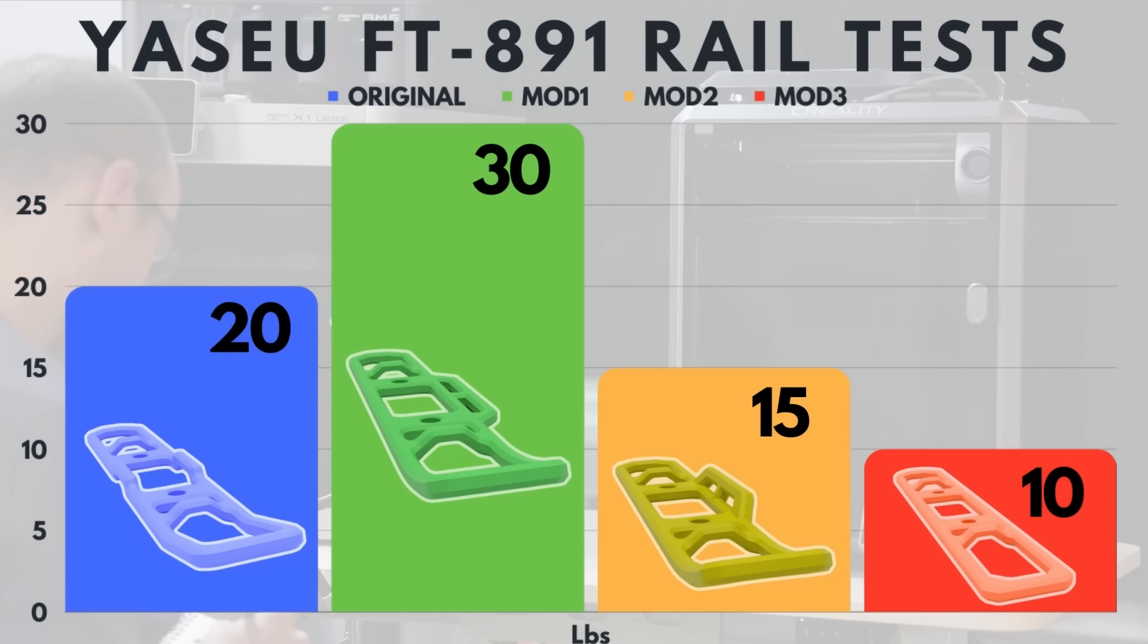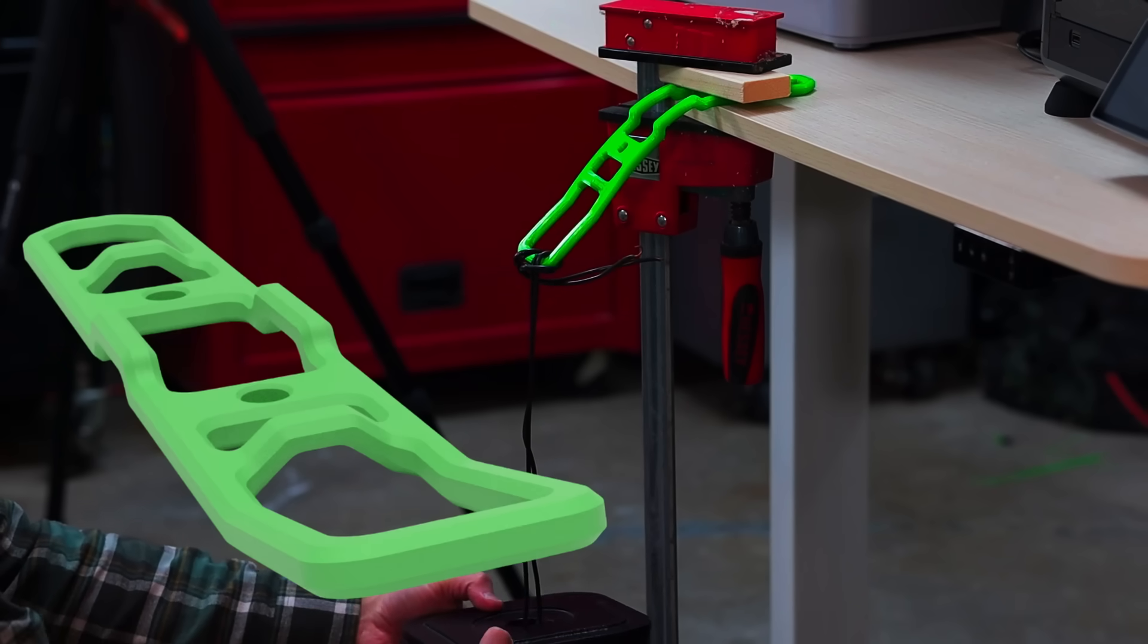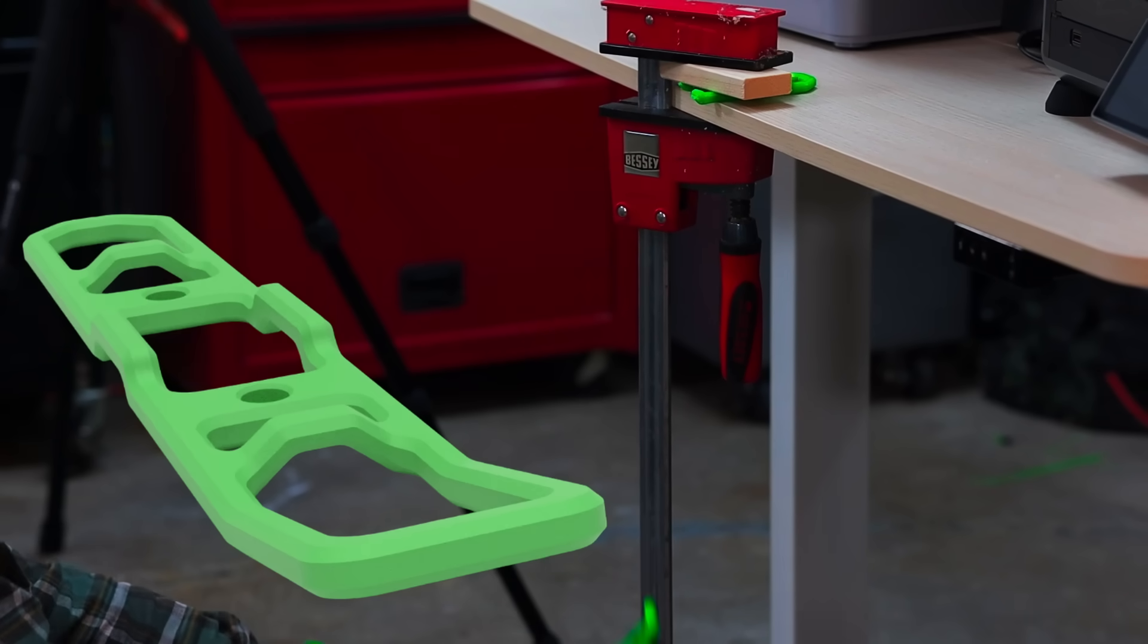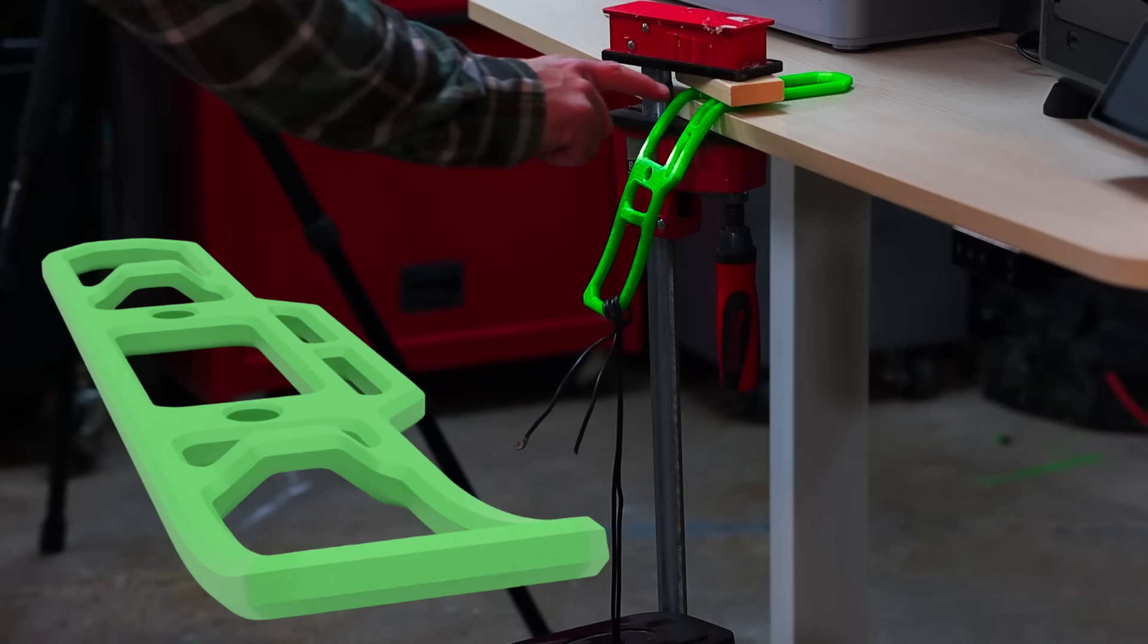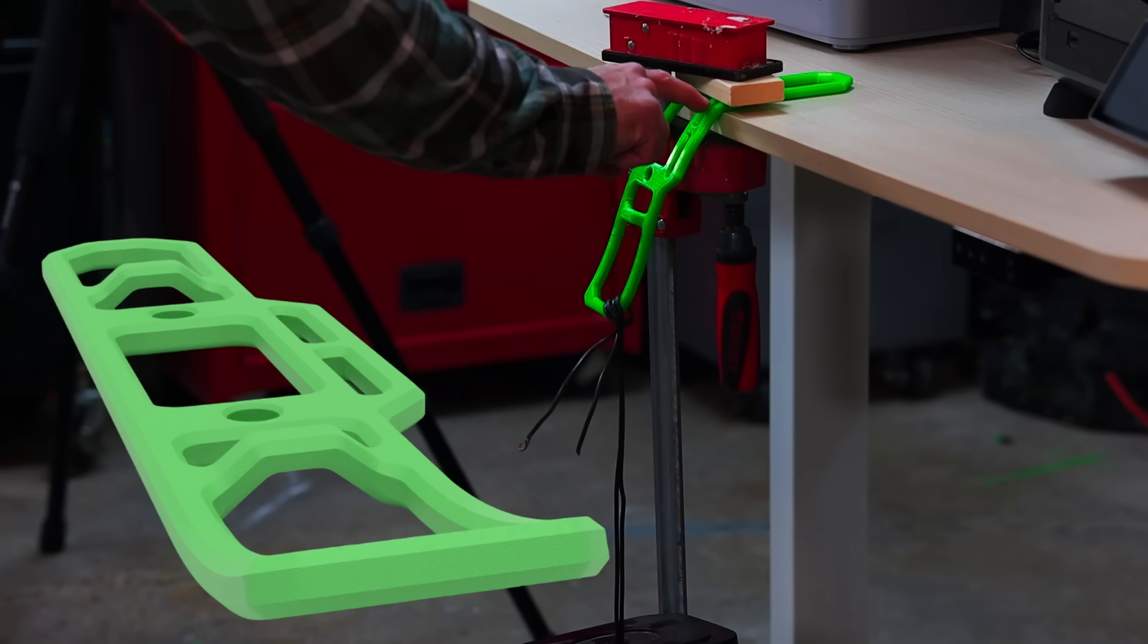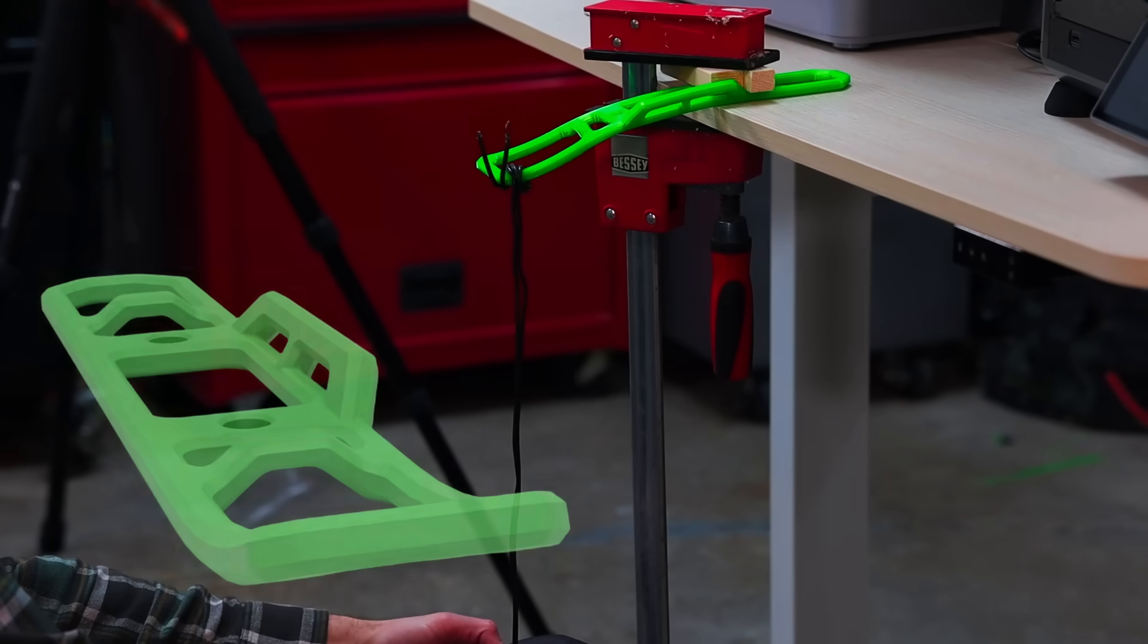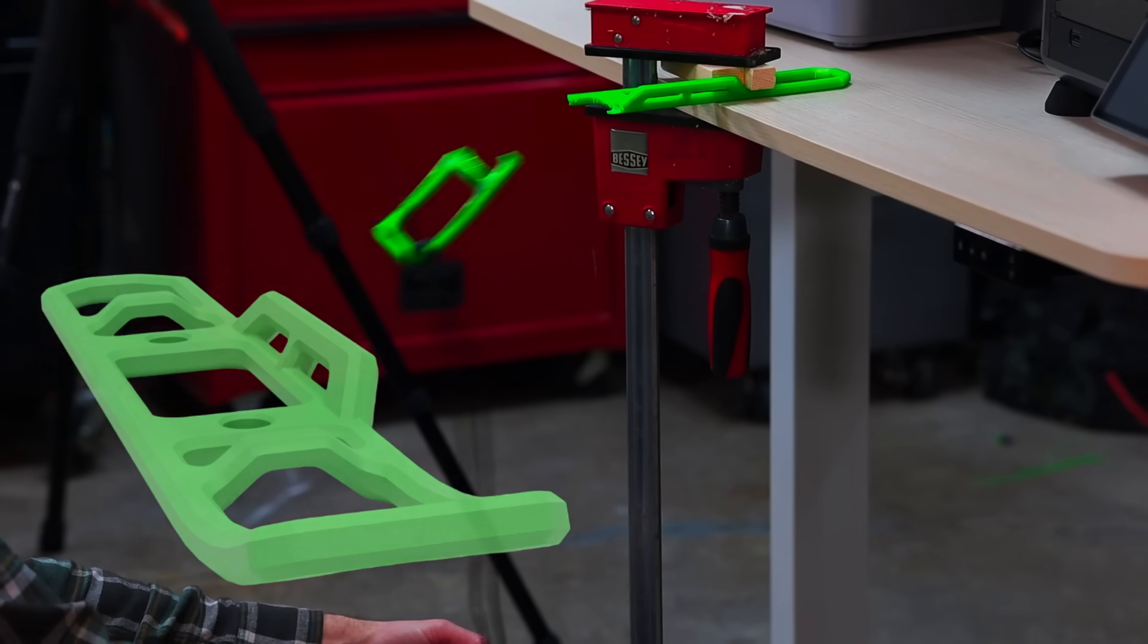The original design was fairly flexible along the entire stick out. Having printed it with no fans, it performed far better than what I expected it to. The mod one was the only version that did not fracture and may have been able to withstand more force had I not left 30 pounds on there for three minutes. Mod number two was more rigid and only flexible towards the end. And stress is concentrated just beyond the strap area where it broke.